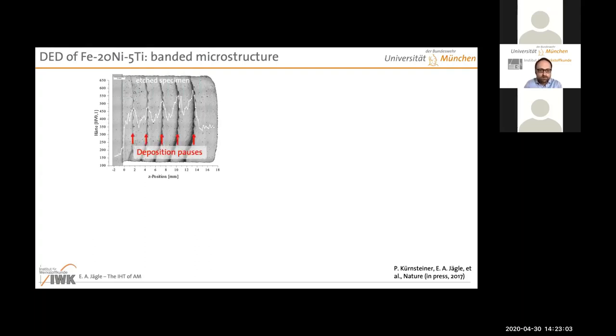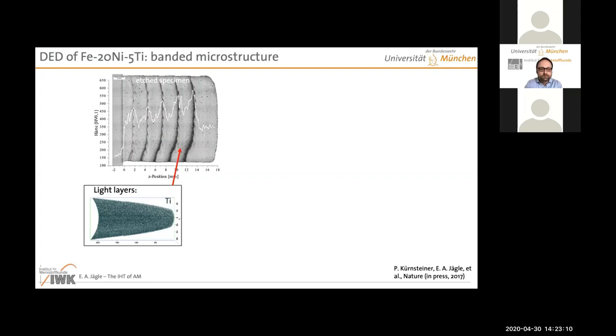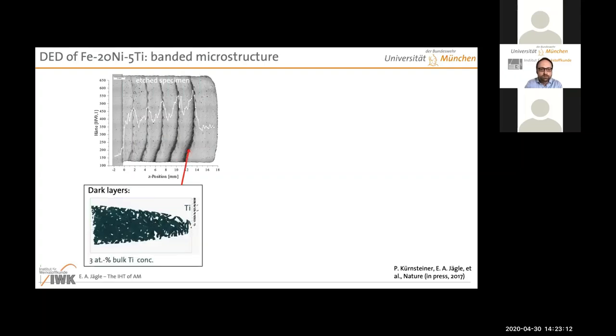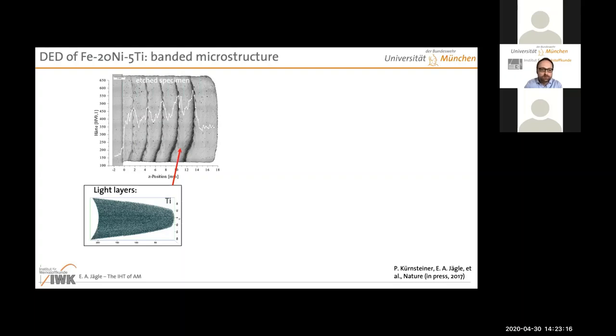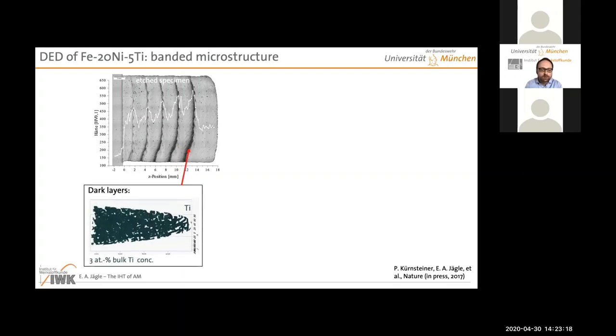And what is happening? Okay, first of all, we could already guess that in the dark layers there would be precipitates, and that is indeed the case. So the light layers are soft because there are no precipitates. The dark layers are harder because there are a ton of nickel 3 titanium precipitates in there. So that's nice to have the confirmation by atom probe tomography, but we basically already suspected that.